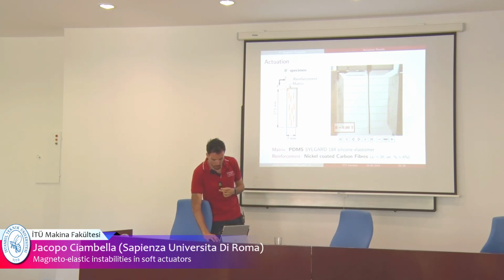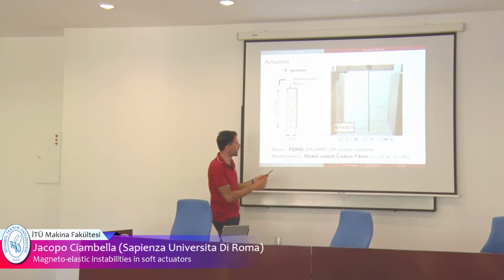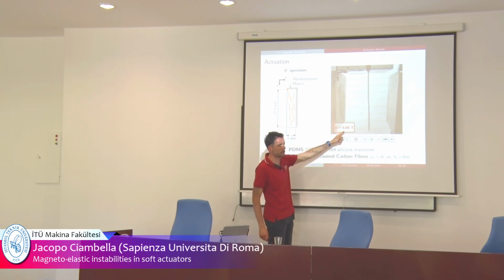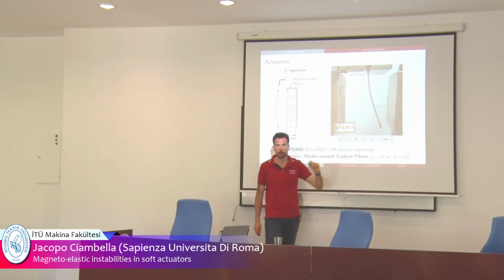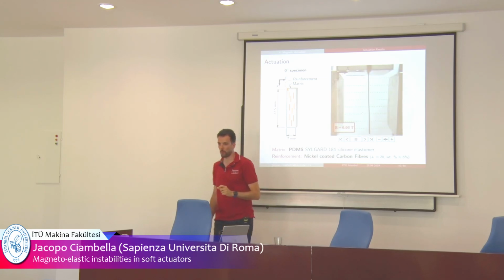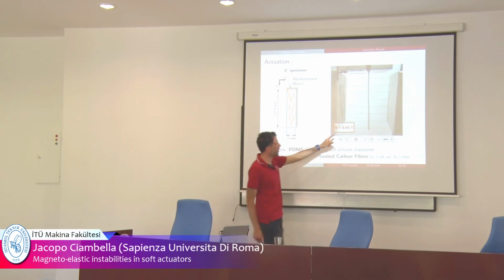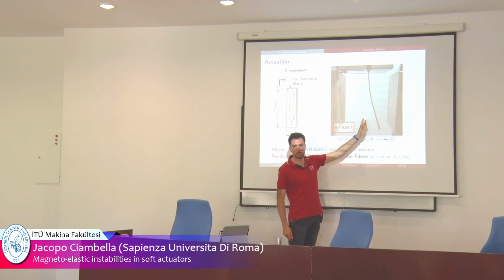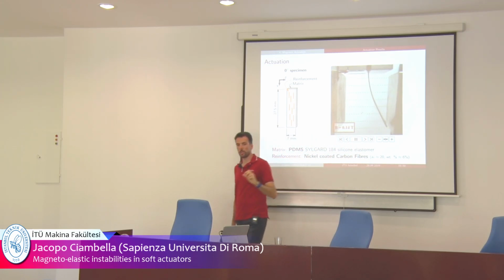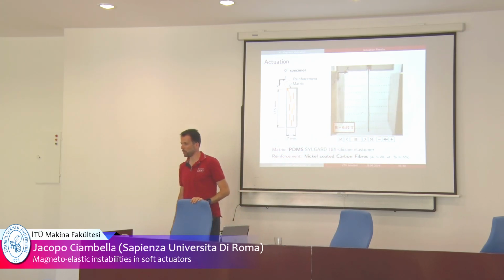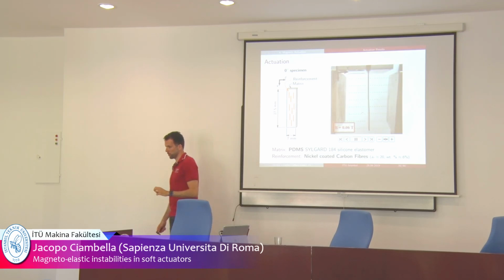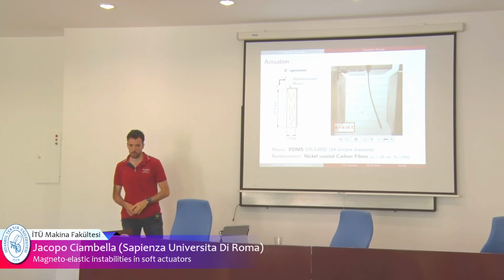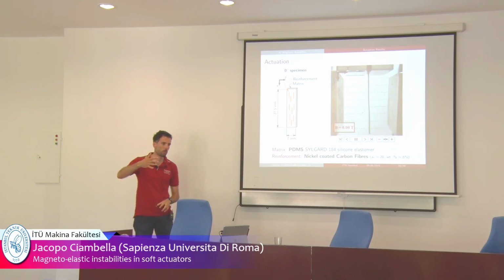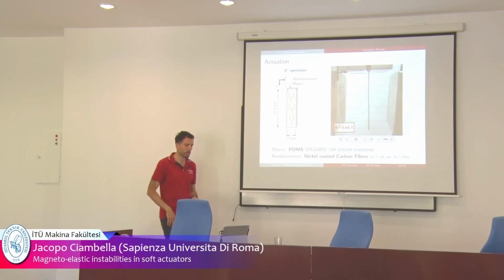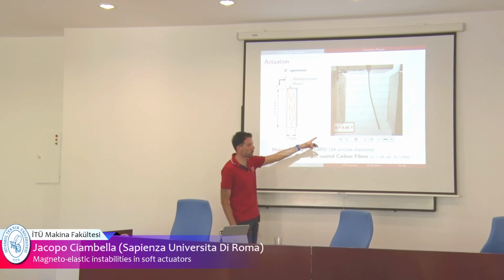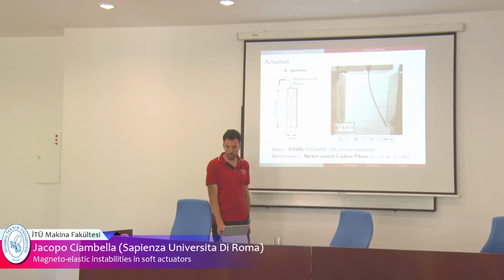And what we did in this experiment: we switch on the electromagnets, we start increasing the field, and nothing happened up to a certain value of the external field. You can see it again, nothing happened, and then, bam, it bent. Initially, the deformation is almost 0. Okay? This is quite strange behavior. We didn't expect to see this. We were expecting to see a slow bending according to the field lines. But then, again, up to 0.06, and then it bends immediately.